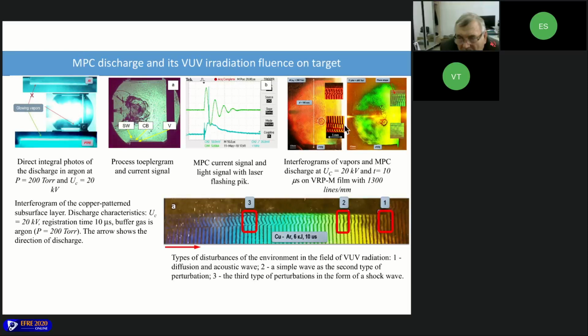There is a plasma vapor contact boundary between the vapor plasma layer and shock compressed gas, and the shock wave between the shock compressed gas and background gas. And the Teflon evidencer allows us to exactly see such effects, but on the metallic target not so clearly.